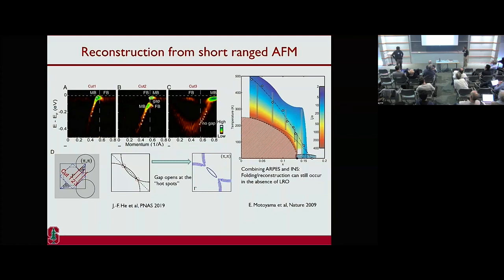We try to explain why you only see this piece and we don't see this piece, because the scattering rate at the antinode is much stronger. In this sample, if you look at the more subtle data, you actually begin to see this piece touch the Fermi level. In that case, we can show quantitatively how much percent of the Fermi surface is for the nodal pocket.